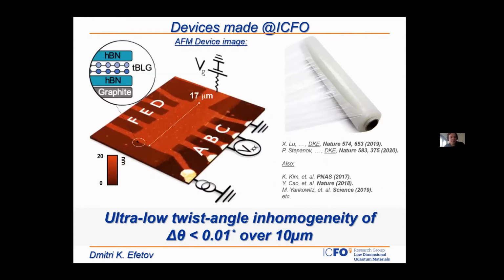Okay, so first of all, let me switch towards the transport measurements in our devices, and in particular, let me introduce the devices and how we make them. The typical devices are made in an encapsulated form, where they're encapsulated in hexagonal boron nitride layers. These layers are just insulators as far as we are concerned. And typically underneath such an hBN layer, we also have graphite layers. In this approximation, we can treat graphite just as a normal metal.